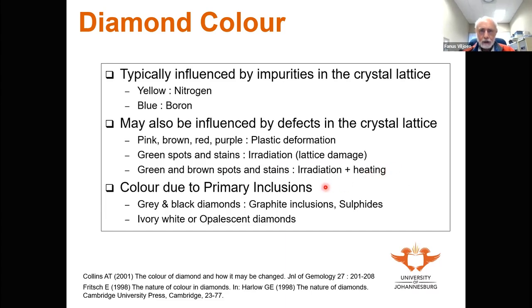Then diamond color due to primary inclusions. We're talking here about things like graphite inclusions as well as sulfide inclusions in diamonds. If you have an abundance of graphite inclusions or an abundance of sulfide inclusions, the diamonds are very typically gray or black. We do also find a subpopulation of diamonds which have an ivory white color or maybe opalescent. And in that instance, the color of the diamonds is most likely due to swarms of micro-inclusions that are distributed throughout the diamond. And the nature of those inclusions is still comparatively poorly understood.